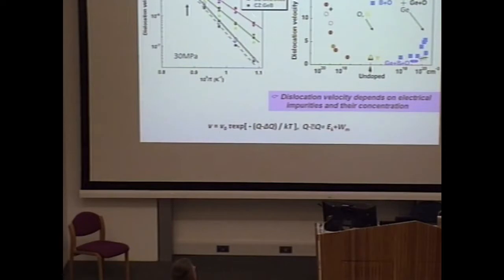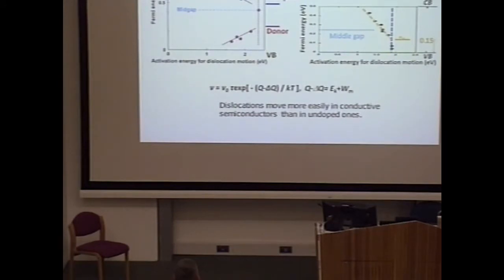And this is the temperature dependence of this dislocation velocity, depending on the impurity concentration and also impurity species. And dislocation velocity can be described by this equation, against the stress and also temperature. And we determine this kind of activation energy. And this is the dependence of the activation energy for dislocation motion. Yes, this magnitude depends on the Fermi energy of the crystals. This Fermi energy changes with the impurity concentration.